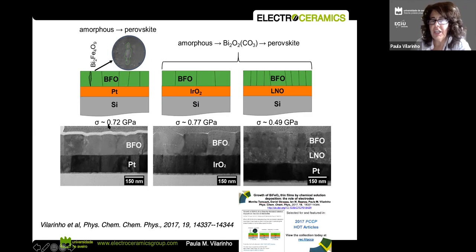As you can see here, the level of stresses is very different. In the case of the lanthanum nickelate oxide, I have a much lower stress level compared with the others. I think this stress level also affects the way the grains grow. And here you can see very columnar grains. So it's not exactly an epitaxial film, but it's something that is really oriented.